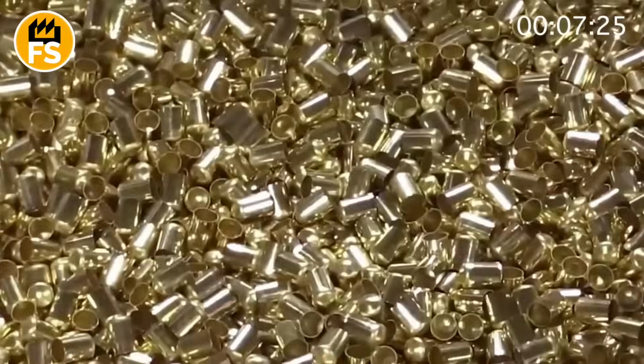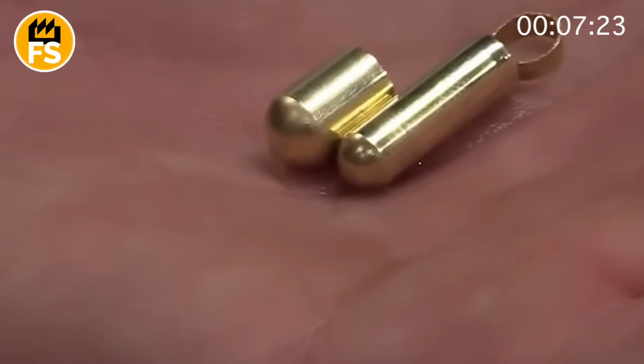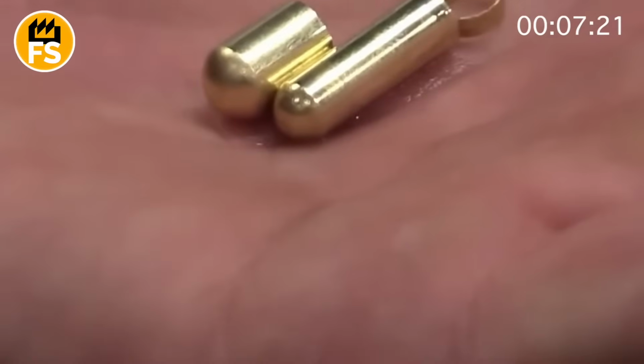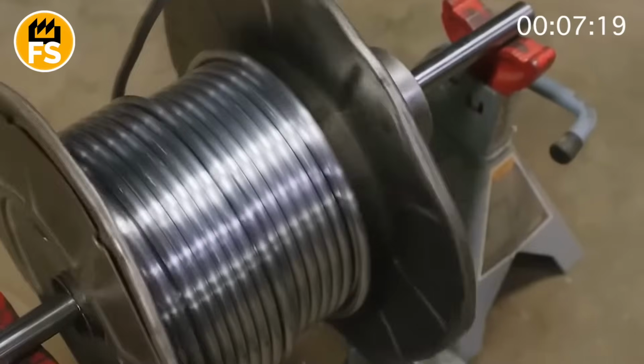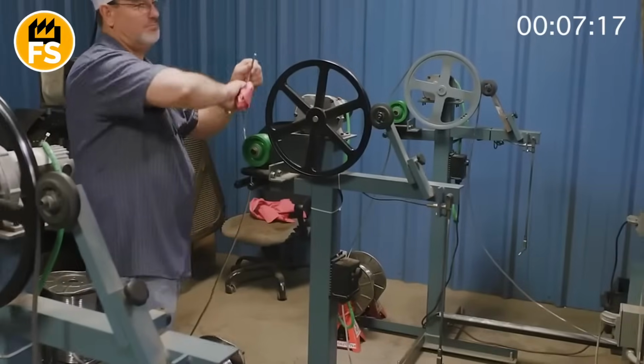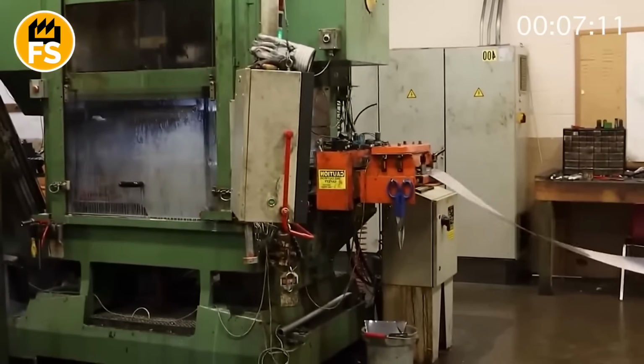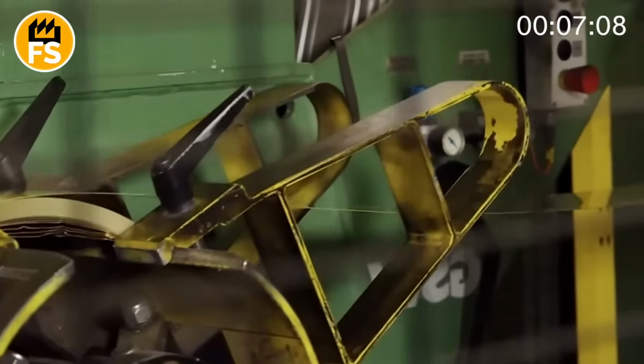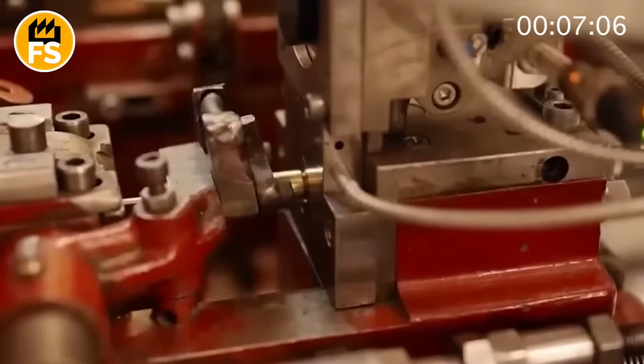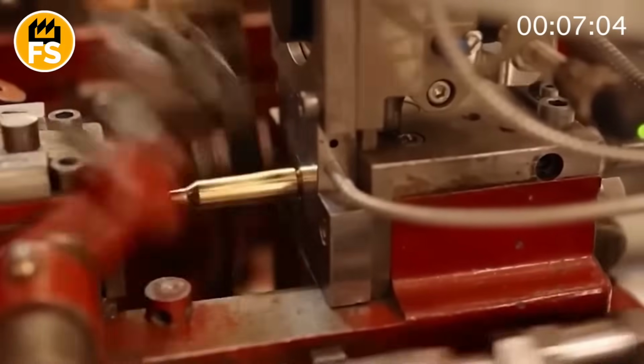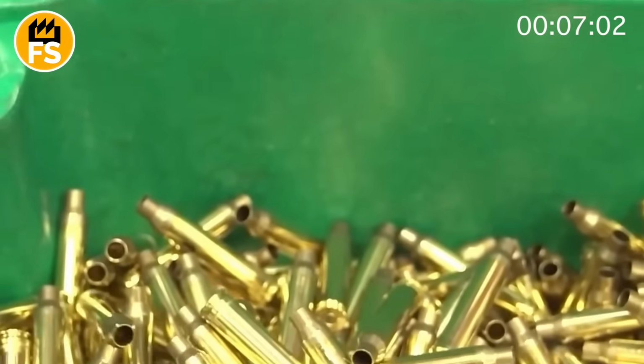They are dipped in lubricant and fed into a hydraulic press, where, under pressure of up to 100 tons, the disc is formed into a primary casing, still without details, just a cylindrical shape. This process is repeated several times, each time drawing the casing a bit longer and thinner. At this stage, the blank already resembles a casing, but is still far from its final appearance.